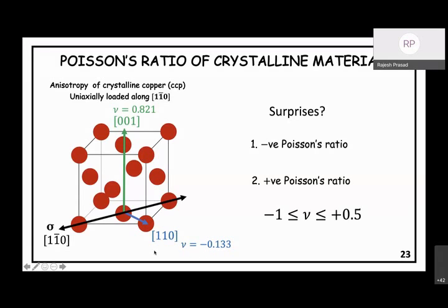So the best experiments you can do, avoiding any measurement errors of the kind of twinning or plastic deformation, you should see that the Poisson ratio is minus 0.133 for this pair of directions. Abhi also has another point. He says, at the end of the day, the limits on Poisson's ratio in one transverse direction will have to be obtained using convexity arguments for the energy, which I think is the same as the positive definiteness.